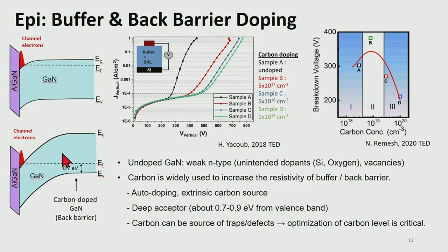Because of a similar reason, we also use the carbon for the buffer doping. It reduces the background carrier density by compensating the n-type dopants in the buffer layers. So if you see this center figure, with increasing the carbon level in the buffer, we can effectively suppress the vertical leakage current across the buffer layers.